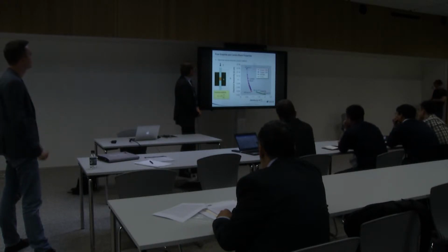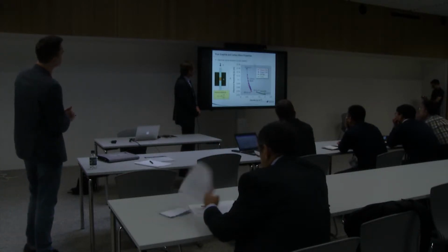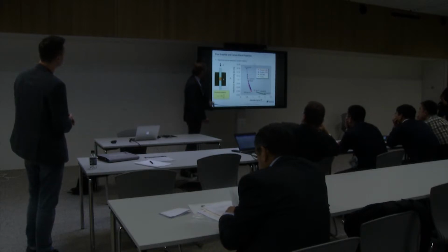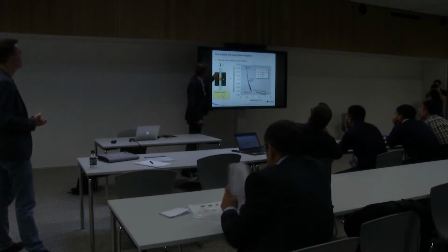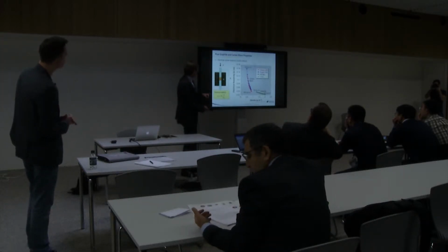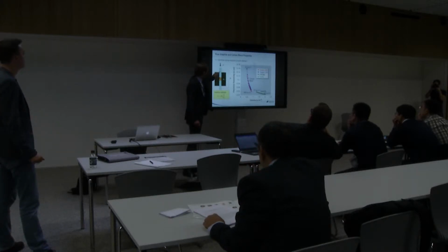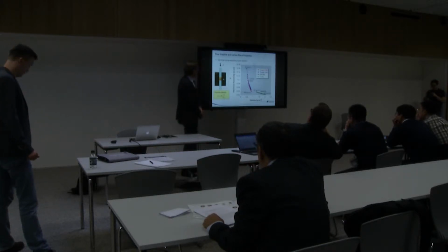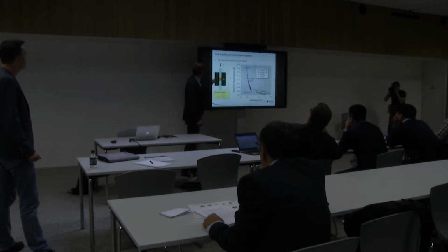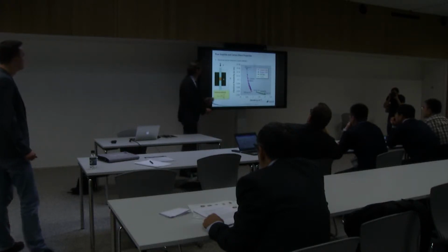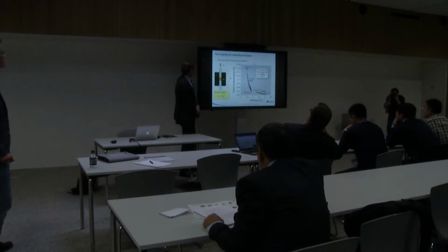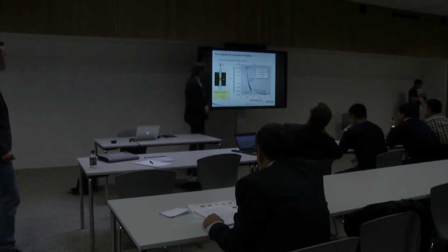What I show here is the electrical volume resistivity of pure graphite and carbon black. We used a die-type arrangement where the sample is put between 2 electrodes, which also act as a piston to compress the sample. We apply a force and an incremental pressure on the sample, and by measuring the resistance between the electrodes, we can calculate the resistivity from the electrode area and the height of the sample. So what you see here is the electrical resistivity of pure graphite and carbon black.